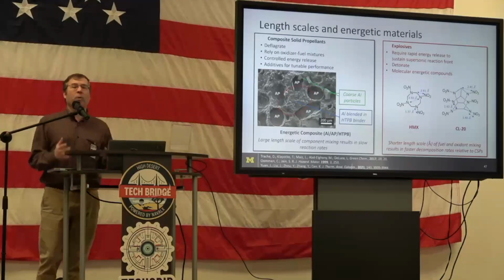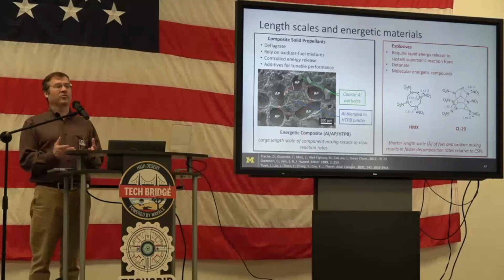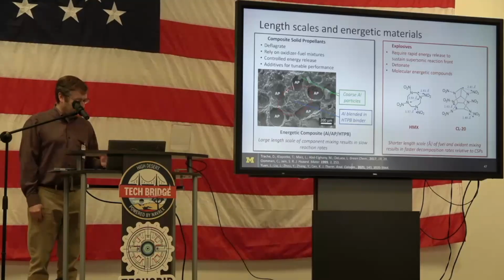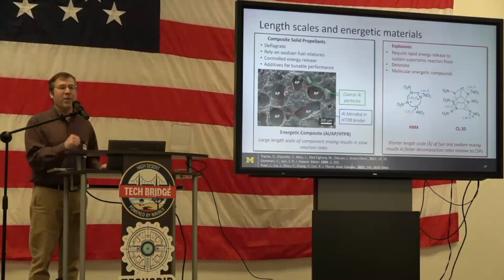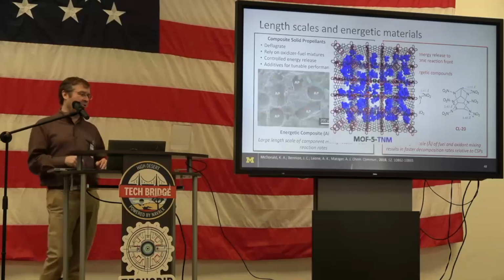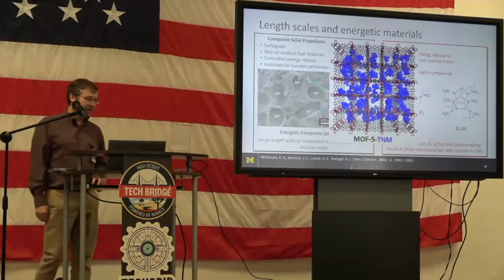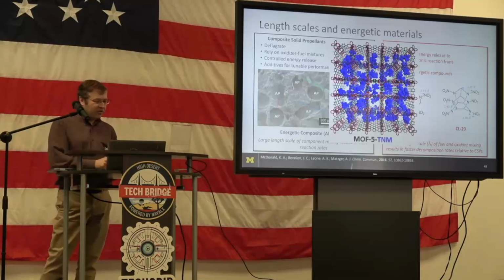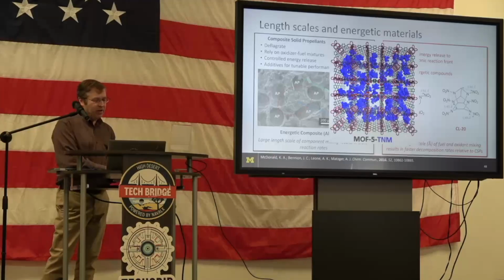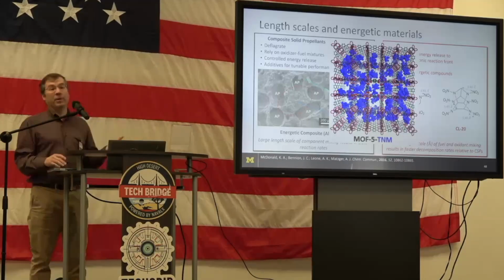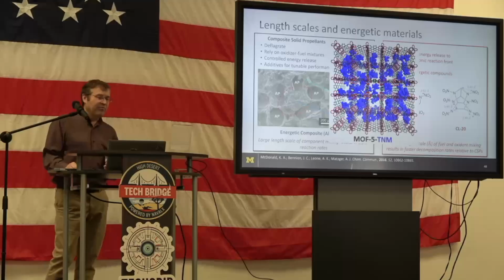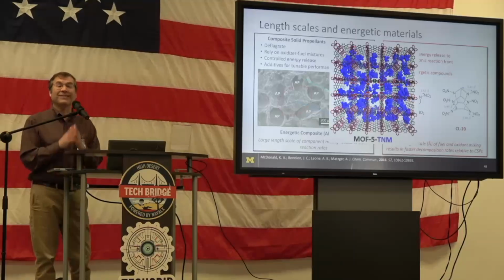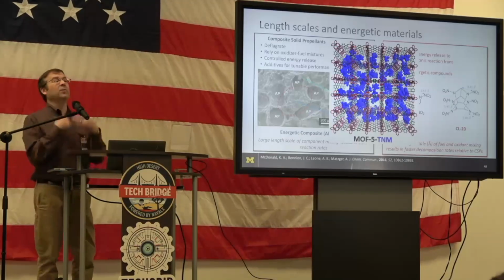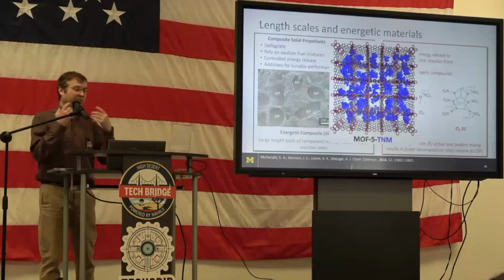So where do MOFs lie on this length scale? I'll show you a picture of tetranitromethane. This is a model in the crystal structure of MOF5. And the distances that we're talking about here are about a nanometer. So it's actually very close mixing, similar to what you get in a molecular species. So we expect fast reaction rates.